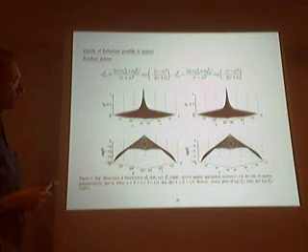So some of the things that you can get just trying to explore this model in a bit more detail, not just to compare with Luigi's results. This is a random system, that's where all the rate coefficients are the same. You get these distributions which are quite broad, and if you've got equal numbers of A and B polymers, you get normal distributions.